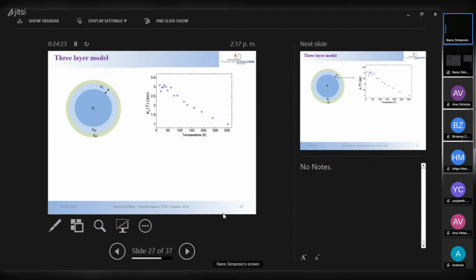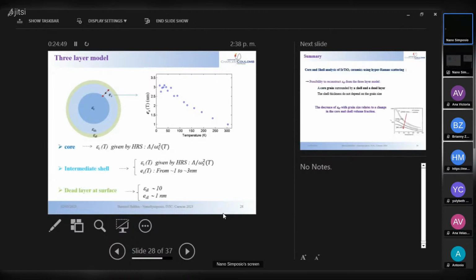Okay, so we know now that the ceramics is done by a 3-layer system, a core plus 2 layers: 1 core, 1 shell, and 1 dead layer. The radius of the shell increases when the temperature decreases. When the temperature decreases, the shell thickness increases. And by the fitting, you have all the information of the core and shell.